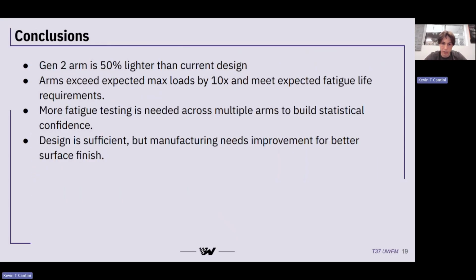The conclusions that we made: the Gen 2 arm was 50% lighter than the current aluminum design. It exceeds our expected loads by roughly 10 times and it meets the fatigue life requirement. The design is sufficient. The remaining work is on the process.